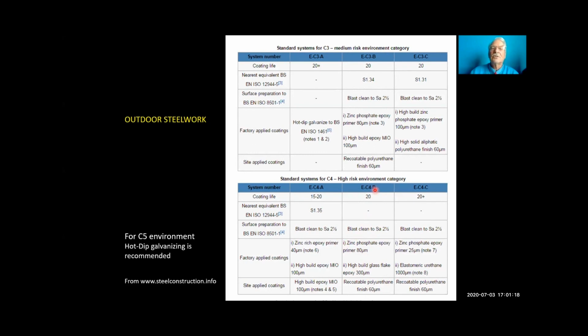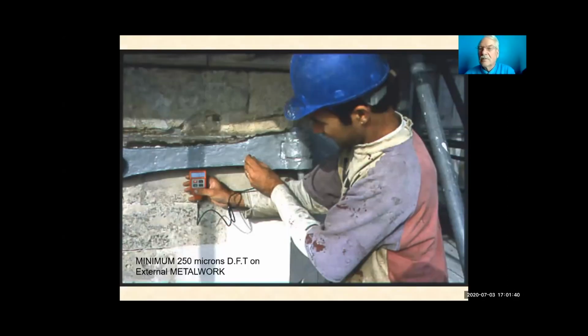I'm sorry to rush through this, but do come back and look at it later if you want to, just to show you that you can expect a life to first maintenance. That means you must do some minor maintenance, but this is the design life of the coating. It should be expected to last 20 years, and may last more if you maintain it properly, provided you blast clean and then put on these coatings in accordance with the manufacturer's recommendations, and that's vital. That's really important. Here's the dry film thickness meter, put it in the hands of the painter, and he can read off how many microns he should be getting at least on the outdoor metalwork. Well done, 250 microns of dry film thickness on outdoor metalwork.